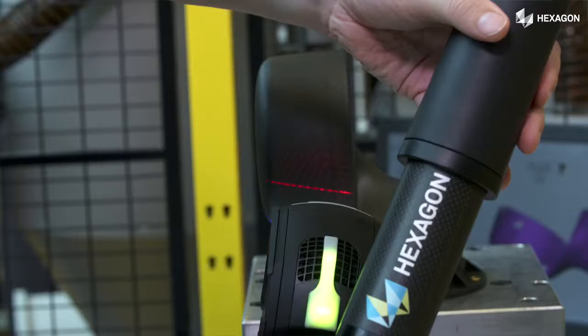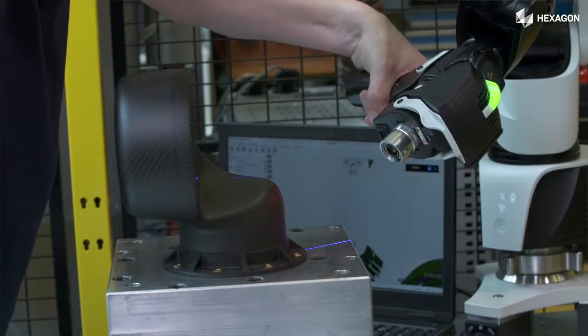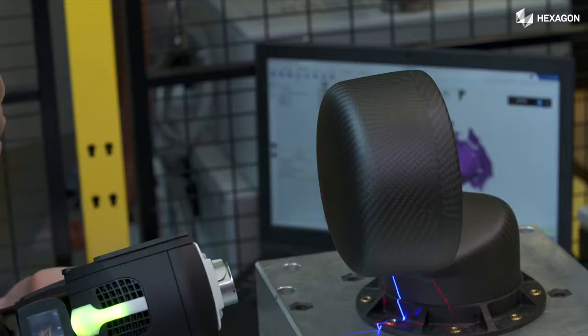With the help of the laser line sensor, we are able to measure deformations from the curing as well as deformations from the inhomogeneous textile structure, which gives deformations on the surface level.